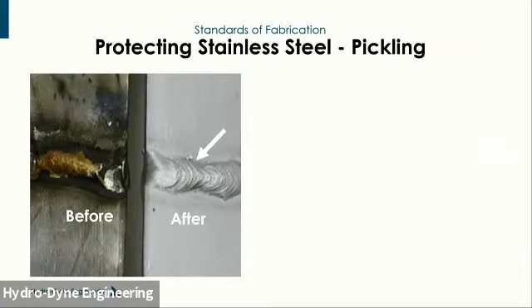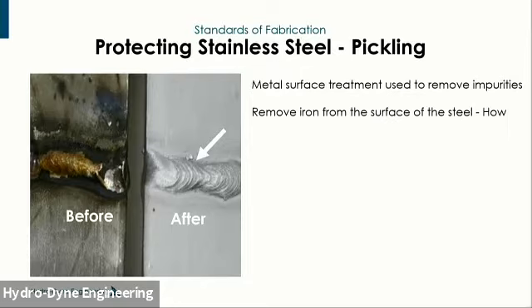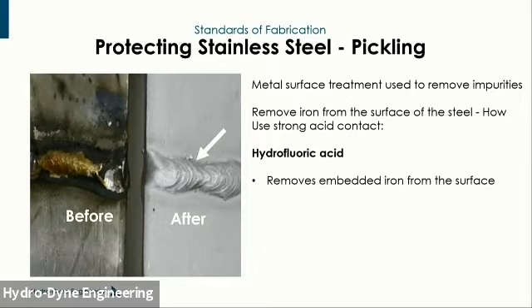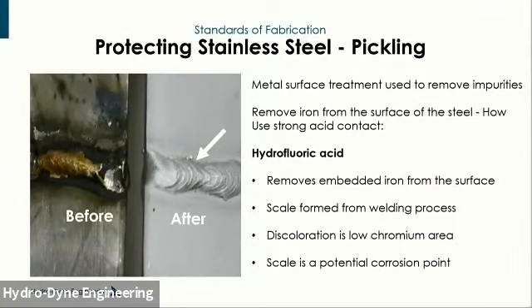So for all the stainless steel for the screens produced, we pickle the steel. And pickling is a metal surface treatment used to remove impurities. We remove the iron from the surface of the steel. You may ask, how do we do it? We use strong acid contact. So we use hydrofluoric acid, and that removes the embedded iron in the surface. And here you can see the dark scale formed during the welding process. That discoloration is a low chromium area, and that's a potential corrosion point over time.